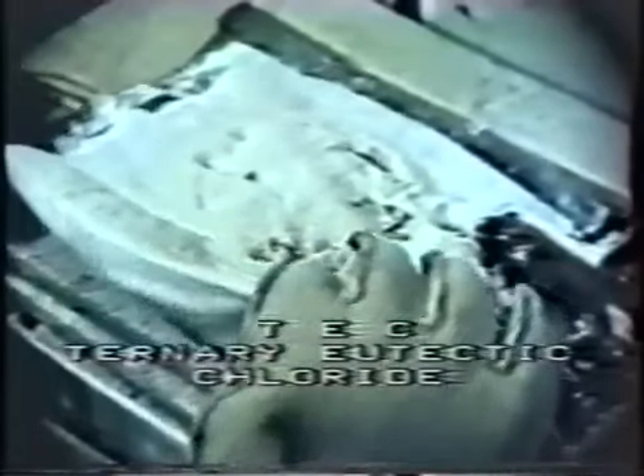This is another way of putting the metal chloride and fluoride salts on a plutonium metal fire, and as you notice, it isn't very effective, simply because as you put the bag on top of the plutonium metal, which is burning as a molten metal, it spews out, and in this case ignited the bag. And as you remove the bag here now, you'll find that all we've done is melt a hole in the bag, and the fire is continuing to burn underneath. This may be a way of containing it, but it's not a very effective way.